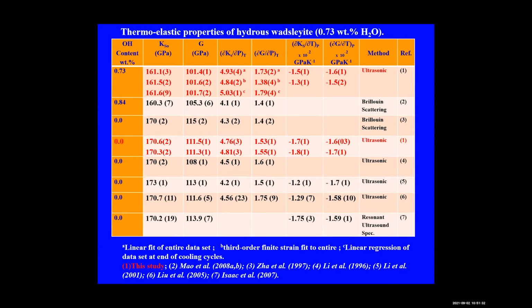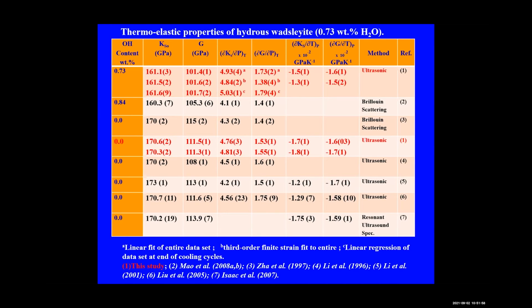Some ultrasonic measurements show a similar discrepancy that could be caused by the residual stress in the boron nitride ultrasonic cell assembly, especially in this case when the temperature is very low for measuring the Wadsleyite samples. We have recently modified the cell assembly during the pandemic by completely surrounding the sample with sodium chloride to minimize the stress on the sample. We just await the opportunity to test out the cell assembly when we have the opportunity to carry out new experiments at the APS.